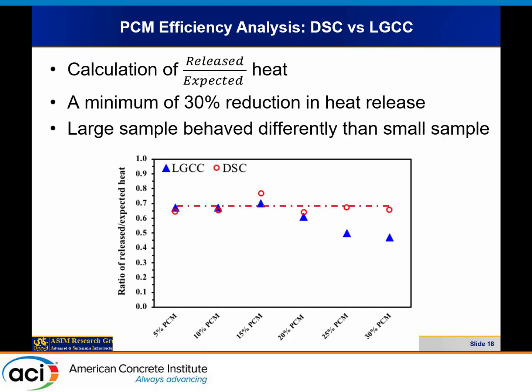So if you look at the DSC result, something similar. As you increase the PCM dosage, we saw about a 30% reduction in the thermal energy. This was constant through all the percentages that we used. So we are missing 30% of the performance of the PCM that we put inside. If you look at the LGCC result for the larger sample, again, it's a flat plateau, and it's very compatible with the DSC result.